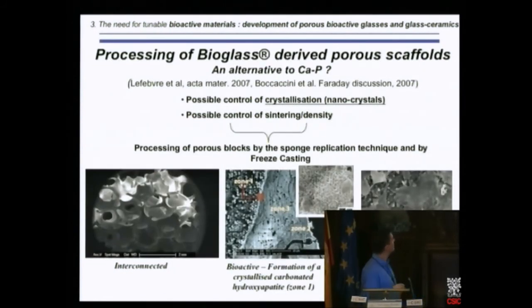So here are the images of bioglass-derived porous scaffolds. We think, because this is the idea of what could be the next option, this can be really an interesting alternative to calcium phosphate. So we have worked on that, especially also with a group at Imperial College, Aldo Boccaccini and co-workers. We have shown that with bioglasses, it's possible to control the crystallization process. We have really nanocrystals, and it's possible to control the porosity by sintering bioglass powders.